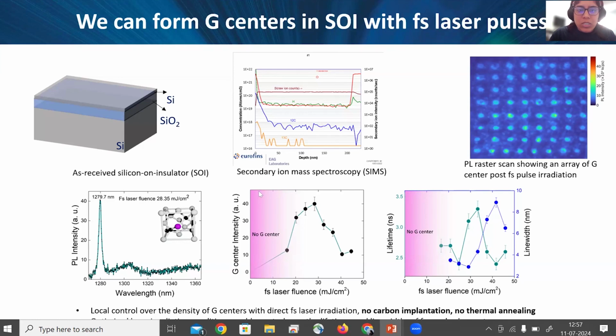And in the center, what you are seeing is SIMS, secondary ion mass spectroscopy measurement, which essentially tells you as a function of depth what is the concentration of the different elements you have in the lattice. You can see that already for oxygen, hydrogen, and carbon, there's enough of these elements present, which essentially tells us that you should be able to make some of the color centers already in this wafer, and you don't need to introduce additional carbon or any other element with ion implantation.